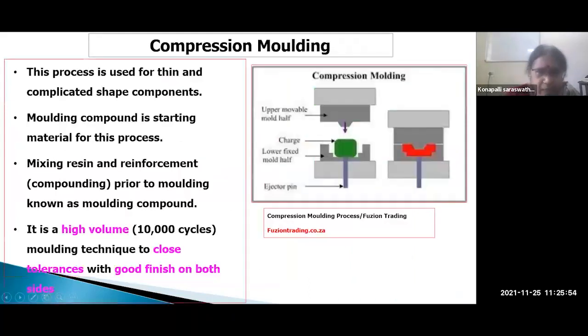Compression molding. This process is used for very thin and complicated shape components. Molding compound is the starting material, mixing resin and reinforcement prior to molding, known as molding compound, or dough molding compound. This is the material, kept in the heated die. This type of component we have to get. In the heated die, this material is charged, and then it is pressed. So this type of component we get from the mold.